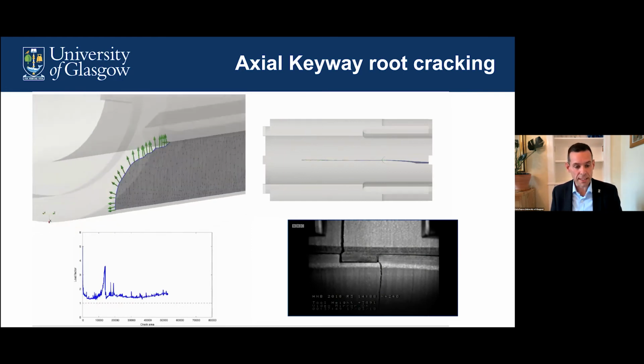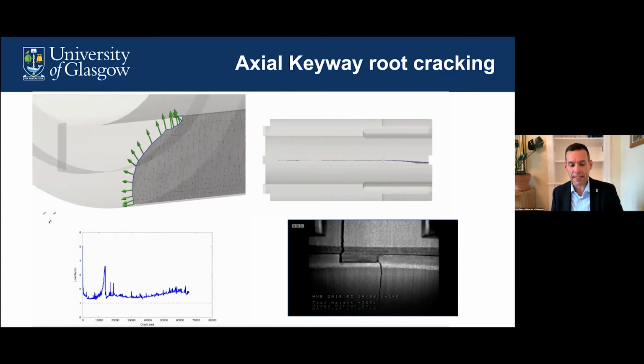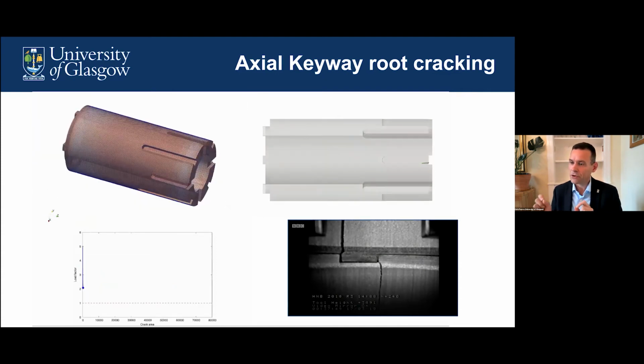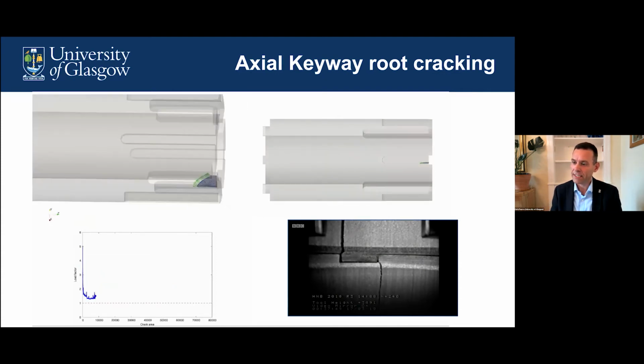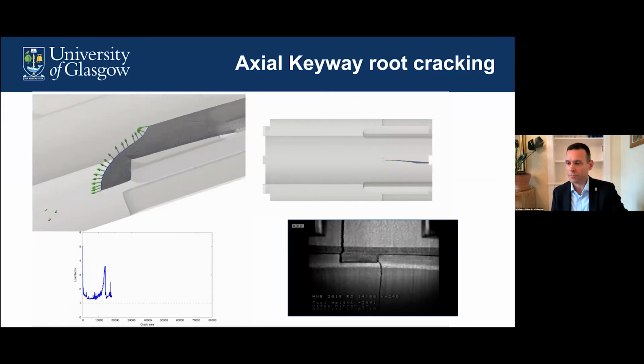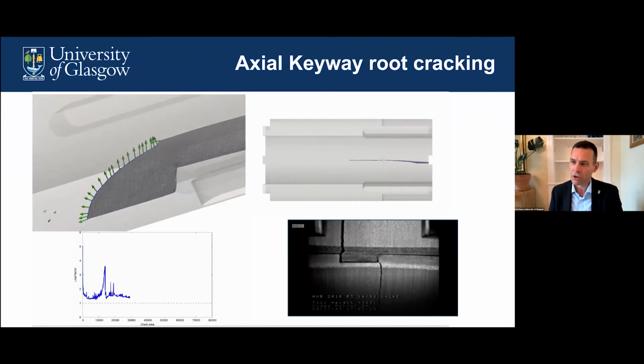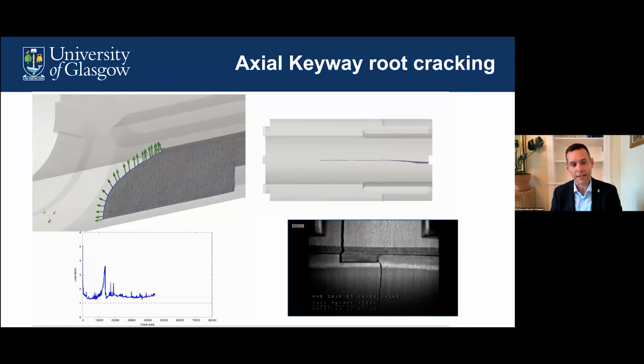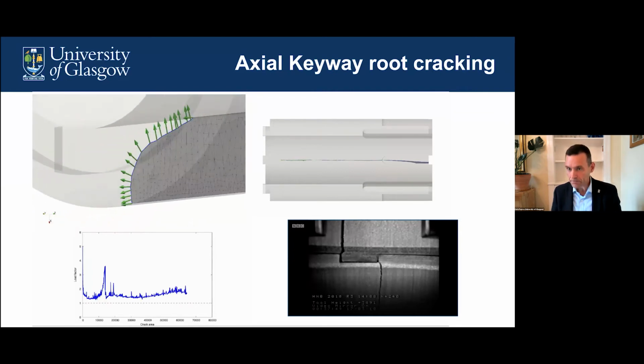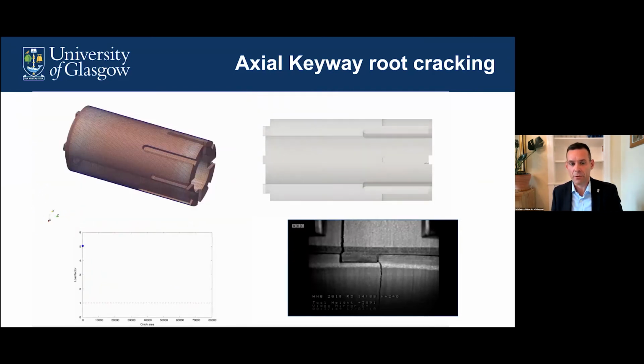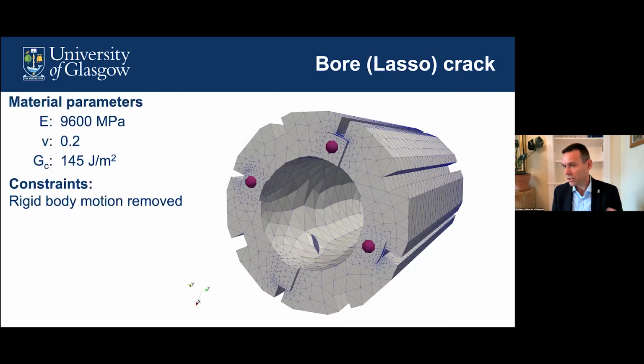And you can also see that there's a slight spike in that graph, and that's where the crack is propagating along the brick and is negotiating this change in geometry, which acts as maybe not a crack arrestor, but it certainly inhibits the crack propagation. So that's a so-called keyway root crack, which matches very closely to what is seen in experiments.